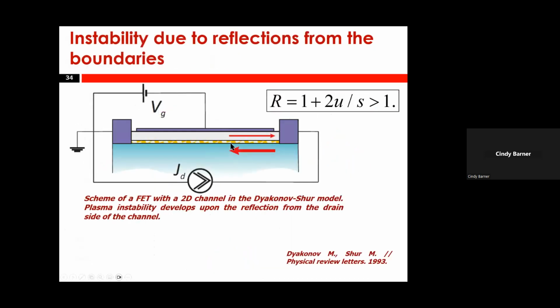And now let's talk about radiation. One mechanism to use is based on the difference in reflection coefficients of plasma waves from two contacts. And as a result, you have this instability, now called Dyakonov-Shur instability. And it has been observed experimentally in several papers. The problem is that practically the power generated is very low. It's about nanowatts. And practical applications for terahertz sources start at about 10 microwatts.